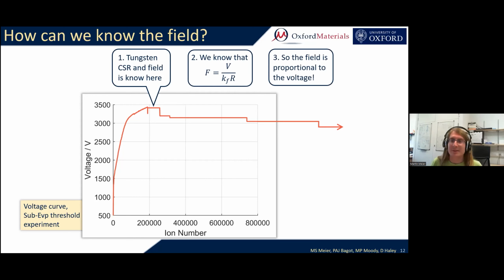What we do is we actually do know the tungsten CSR just at a point in time where the sample stops evaporating. And we also do know that given a constant tip radius and given a constant geometry, the field is actually just proportional to the voltage. And this allows us to calculate the electric field at any voltage below the evaporation threshold just through a linear interpolation. And all we need to do is make sure that we never accidentally change anything at the geometry of our sample. And now with this, time for some results.